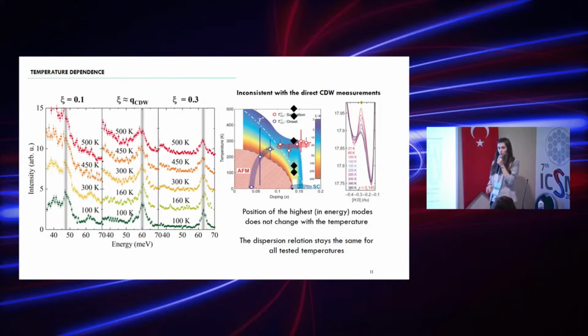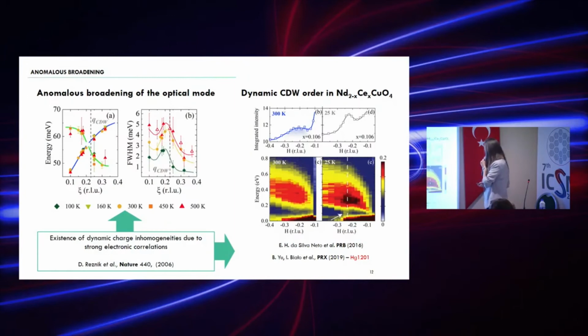But again, we don't see any influence of temperature on the dispersion relation, while the charge density wave is clearly a temperature-dependent phenomenon. So again, charge density wave doesn't change the phonon dispersion that we probed. However, we've seen some anomalous behavior. And here you have, once again, the blue mode and the green mode, but for different temperatures. And we've seen an anomalous broadening of this blue mode. And that's the picture in the middle.